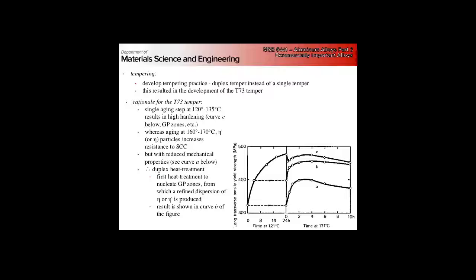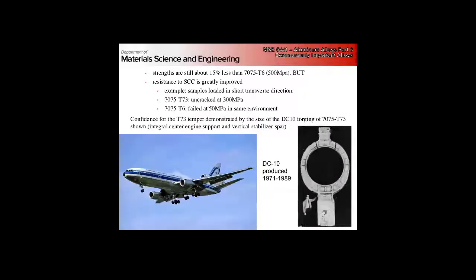So the idea was a duplex heat treatment. We age first at 120, cool down, and then bring it back up to 160. This allows the GP zones to nucleate here, and then the fine dispersion of the eta and eta prime to nucleate on the GP zone, and we can recover much of our strength with an increased resistance to stress corrosion cracking.